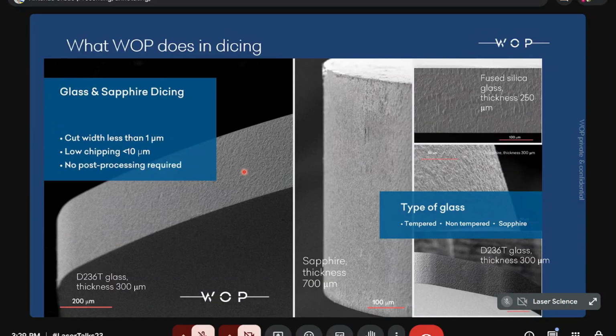This example presents D236T glass, which is quite popular glass for semicon applications. And you can see that the cut surface is quite clean. Fused silica, again, very nice. Sapphire is not so nice, with a little bit bigger chipping because of being a crystalline material, and these crystalline planes pull your cuts a little bit into the material. So that's why it is not as clean as glass, but still quite good. And again, our patents are related to tempered, non-tempered glass, sapphire, so whatever you want.